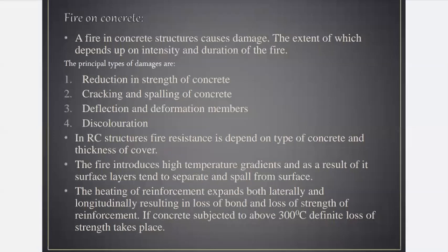The heating of reinforcement expands it both laterally and longitudinally, resulting in loss of bond and loss of strength of the reinforcement. If concrete is subjected to above 300 degrees centigrade, a definite loss of strength takes place. Loss of strength means which loss? Compressive loss is there and tensile loss will also be there. So provide more clear cover for your concrete and reinforcement steel.